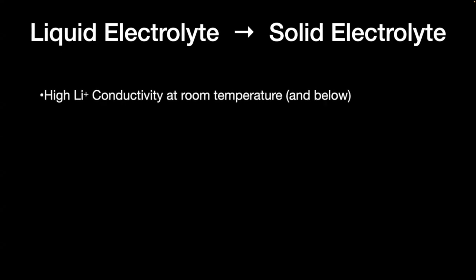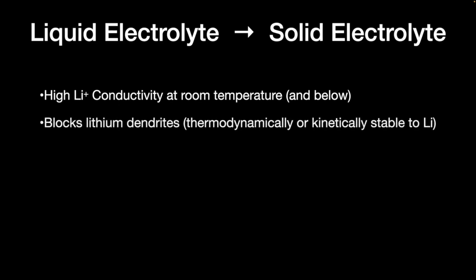All right, so if we're going to move from liquid electrolytes to solid electrolytes, we have some choices. And in fact, we can write down a tick box of what the requirements are if we're going to make this transition. Clearly we need high lithium ion conductivity, hopefully at room temperature. Not all these solid electrolytes conduct at room temperature, but hopefully at room temperature and below. If you're going to work with lithium, you need to block lithium dendrites. And actually, Eric will talk a little bit about the mechanical properties necessary to do that. And that means you either need thermodynamic or kinetic stability to lithium as well at the interface.